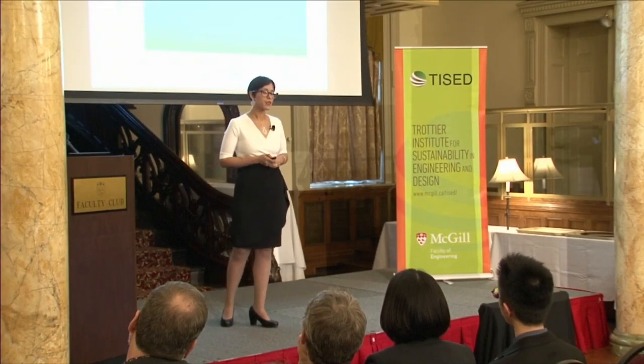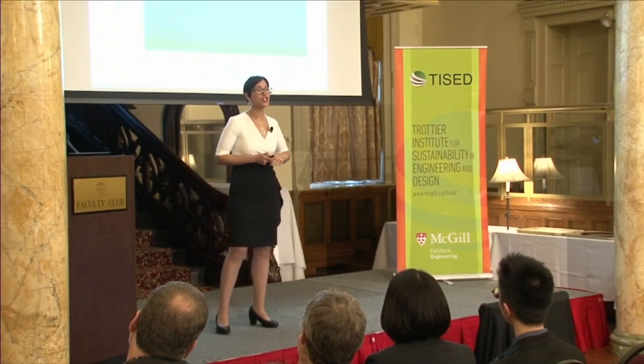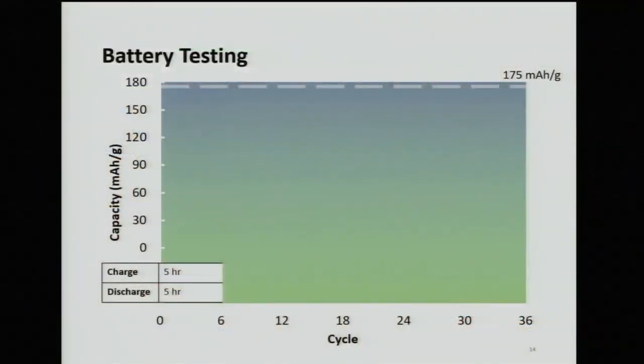So now, we're going to take this battery and charge for 5 hours and discharge for another 5 hours. So one cycle of charge and discharge takes a total of 10 hours. And for the EPD electrode, what we find is that we reach the 175. And there's a gradual decrease. This is expected in a lab setting. When we look at the conventional, we find that it's much lower. It doesn't reach the 175, but it's at an equal degree of degradation.